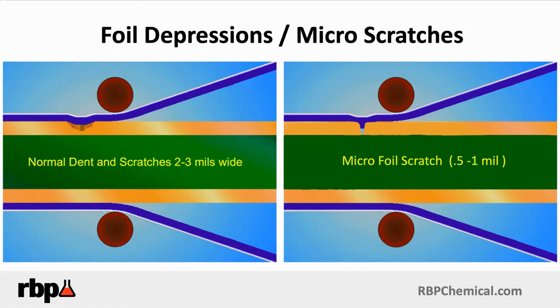And then what's going to happen during etching? The etchant is going to come underneath here, and because it's an area that it can find, basically like a tube or a straw, it's going to go up under there and just etch away the copper, and you're going to have an open on your inner layer, and you're going to be very, very disappointed. So quality of your surface is very, very important. Make sure you don't mishandle the copper foil. Inspect it if you have to. If you have poor quality foil, send it back, particularly if you're doing finer lines and spaces.